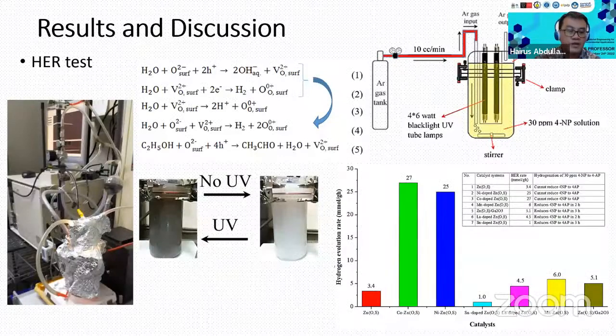Then we do the HER test, the hydrogen evolution test. This is a typical photo system for the hydrogen evolution test. Here is the reactor. We first flow in argon and remove all the atmospheric gases. After that, we close the door and turn on the light. Then at certain time intervals, we take a sample of the gas and inject it into the GC, gas chromatography, and we can see the peak related to the hydrogen evolution reaction.